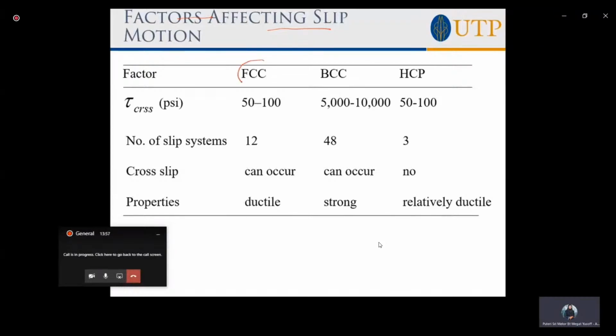We're going to compare between FCC and BCC. HCP, you just look at it. We are not going to deal with HCP because we didn't learn about the crystal structure anyway. So how about the critical resolved shear stress? That is the minimum tau that you must achieve in order for the system to slip. So there must exist this minimum value. For FCC, the value is 50 to 100 psi, pounds per square inch. But when you look at BCC, it is 5,000 to 10,000 psi. So such a huge difference in terms of the minimum shear stress that is required for slip to happen. So this is the minimum for slip.